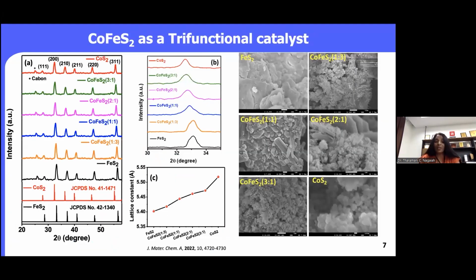So here we are developing cobalt iron sulfide as a trifunctional catalyst. We have been working extensively on this, but I have taken only one example here. This has been synthesized using hydrothermal treatment with the chloride salts of both cobalt and iron. The microstructure has been confirmed by XRD, as you can see here. After the insertion of cobalt into the iron sulfide, you can see there is a shift and also an increase in the lattice constant. This is due to the replacement of iron by cobalt in the structure.